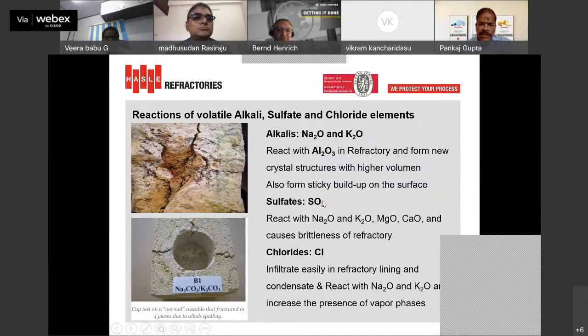In the same way, sulfates react with the different alkalis, and when they react with the refractories, they cause brittleness of the refractory, and the refractory becomes very weak and fails early. Then chlorides have a tendency to infiltrate very easily into the refractory lining and condense in the refractory. When alkalis come, they react with it and form vapor, which makes the refractory not perform.